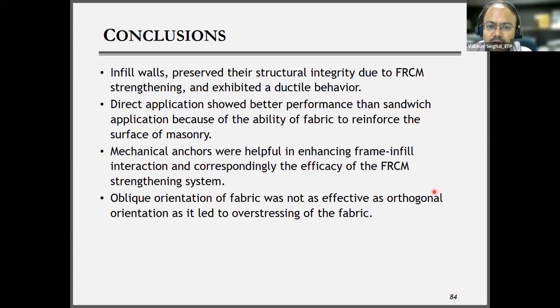Now, the final concluding remarks are that this type of strengthening technique, the reinforced cementitious matrix, is quite promising. It is easy to implement, but we need to do a lot of work, especially to find out what could be the acceptance criteria for designing these reinforced cementitious matrices. Acceptance criteria in terms of the effective strain and the effective stress they can take, because the effective stress or effective strain will depend on the interaction of the reinforcing material within the cementitious matrix, and also the interaction of this reinforced cementitious matrix with the substrate.